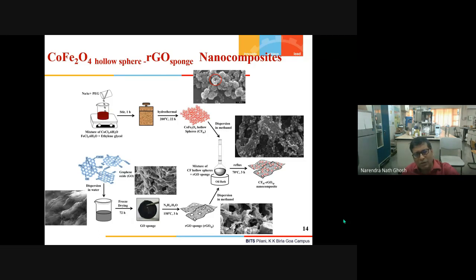And when we did the SEM, we found that these spheres are forming. Basically, these spheres are the agglomeration of small cobalt ferrite nanoparticles, and they are hollow in nature.